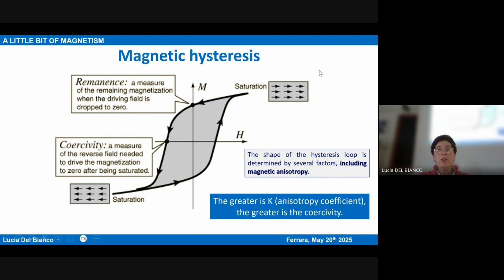Okay. So of course, if your ferromagnet is subdivided into domains, as we have just said, there is no net magnetization, but you can saturate it, so align all the magnetic moments of your ferromagnet, if you apply a strong enough field. And therefore you reach the saturation. And when you decrease the field back, something very interesting appears, which we all know, the phenomenon of magnetic hysteresis, which means that the magnetization does not revert back to zero, but you have a remanent magnetization.